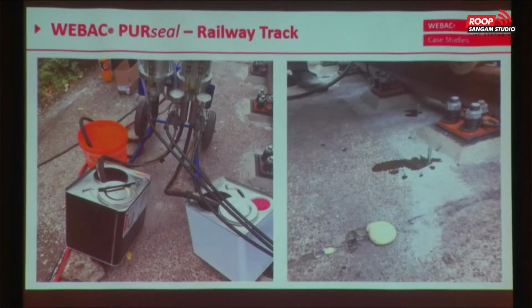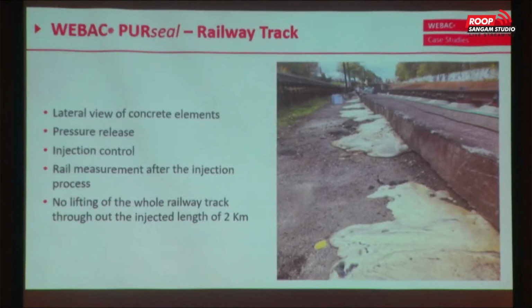We drilled through, injected. Here you see the joint between 2 concrete slabs. And don't be scared about this. This is wanted because I want an opening for a pressure release. That means each side, it looks more than it is, but each side the pressure has to go somewhere because the resin develops a foam, and the foam creates pressure anyway. And like I said, there was no lifting wanted, so we released that, and on that length of 2 kilometers, they measured it with a special railway measurement train. We have no lifting, so that was the target there, and they were satisfied. The target was to consolidate the gravel and the ground under that point.